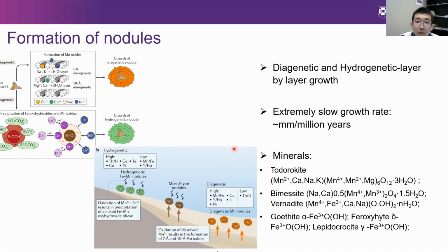The growth of nodules is an extremely slow process. The growth rate is just in the order of millimeters per million years. That means once you harvest the nodules, they are just gone. If you consider a commercial mining operation, we should consider whether there will be enough good nodules for production, like several million tons per year that can last 20 or 25 years. So exploring and assessing the abundance of nodules is quite important.